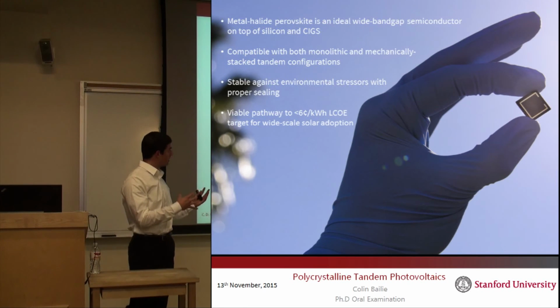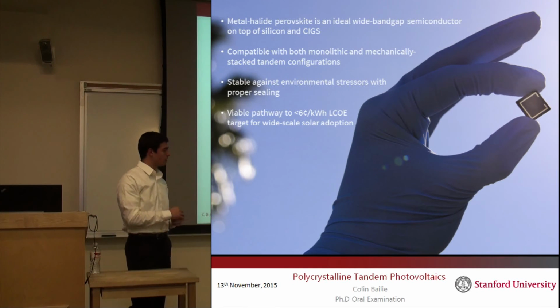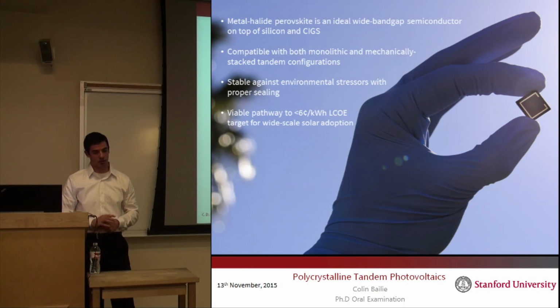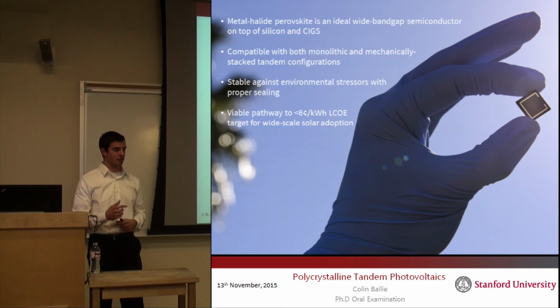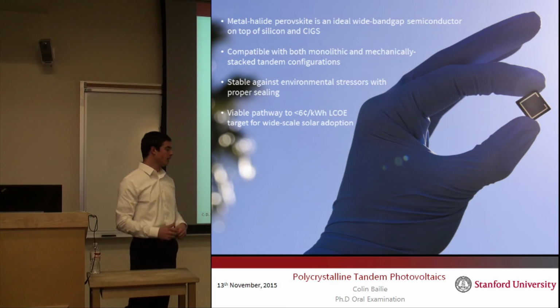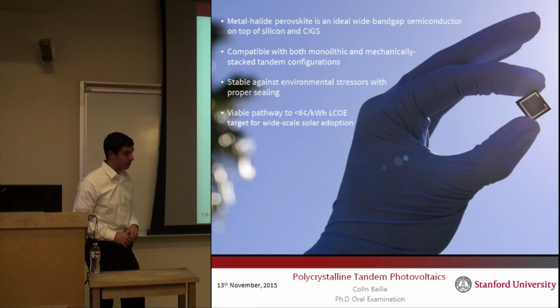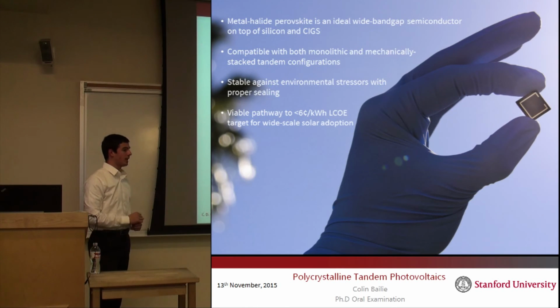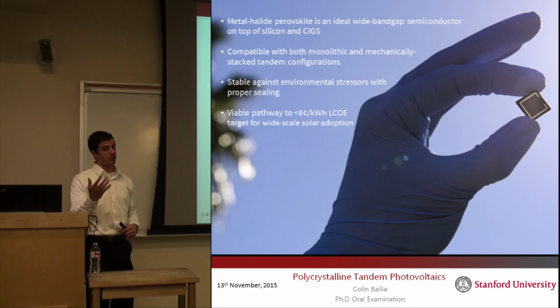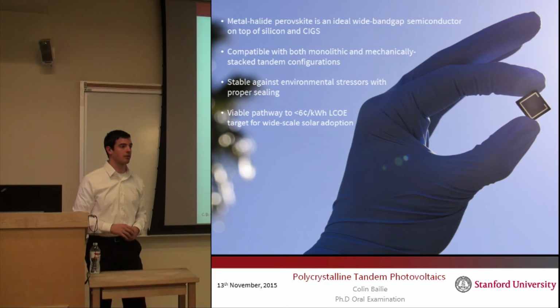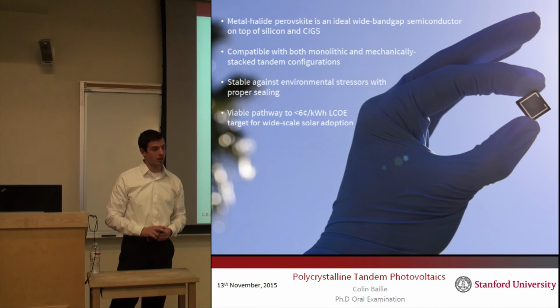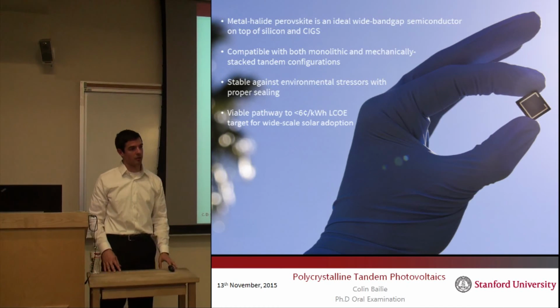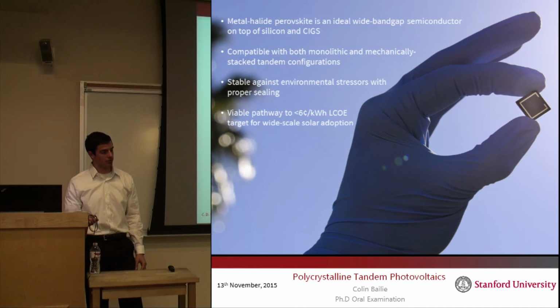And then number 3, making a 20% perovskite solar cell, that's quite doable. But in order to get a 30% tandem, you need something that's highly transparent in the infrared. And so these semi-transparent solar cells I was making today are somewhere between 70 and 80% transparent. But if you really want to get up to 30% efficiency, then you need something that's more like 90% transparent. So working on the optical design of the perovskite stack in order to get 90% transparency would be number 3.